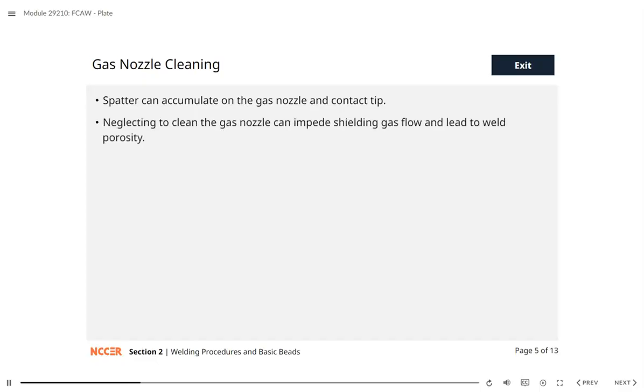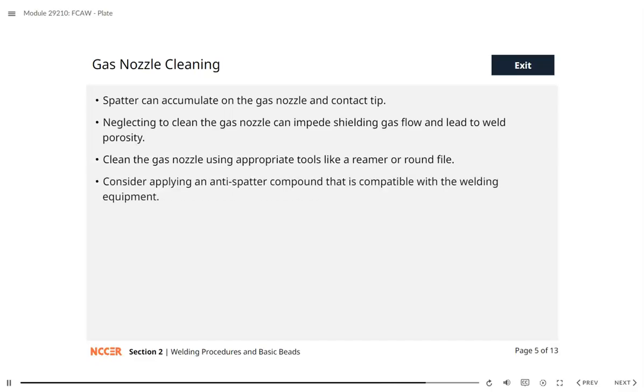During FCAW, spatter can accumulate on the gas nozzle and contact tip. Neglecting to clean the gas nozzle can impede shielding gas flow and lead to weld porosity. Additionally, when making out-of-position welds, spatter buildup in the nozzle can cause a short circuit, resulting in the nozzle sticking to the workpiece. To prevent these issues, clean the gas nozzle using appropriate tools like a reamer or round file, and consider applying an anti-spatter compound that is compatible with the welding equipment.